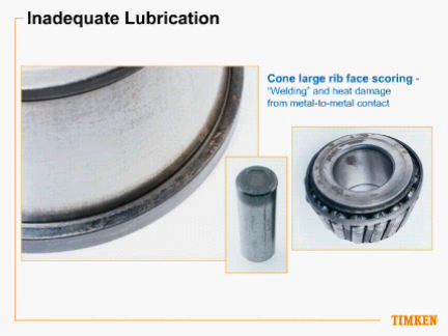All right, now we're going to look at some examples of damage related to lube. I know I said earlier that most damage to a bearing can be related to lube, and you'll see why as we go along. This cone shows heat generation at the cone large rib and subsequent damage to the roller large end. This will be the first area of a bearing to show evidence of excessive heat, because the interface between the roller and the rib of the cone is the only surface of the bearing that has sliding contact. If you look at those photos, you notice how it's darkened and discolored on the roller large end and the rib face, which is where that roller rides against. That's due to the heat buildup from the sliding contact.